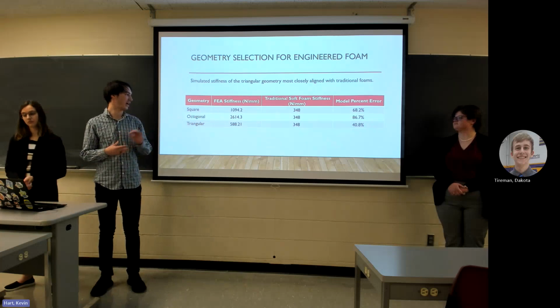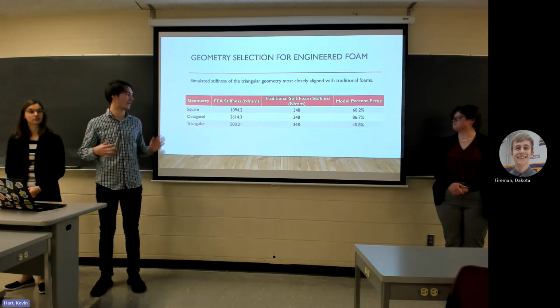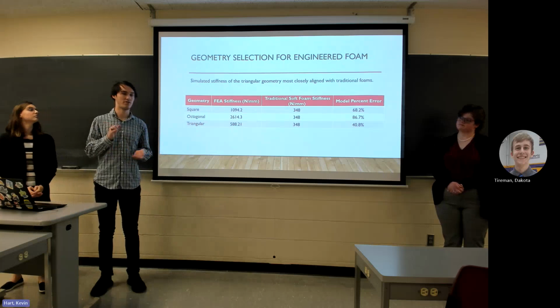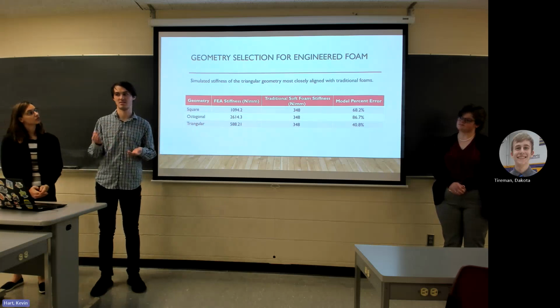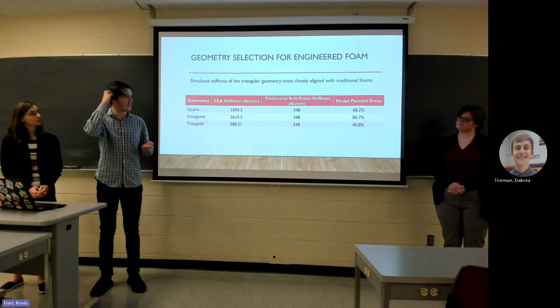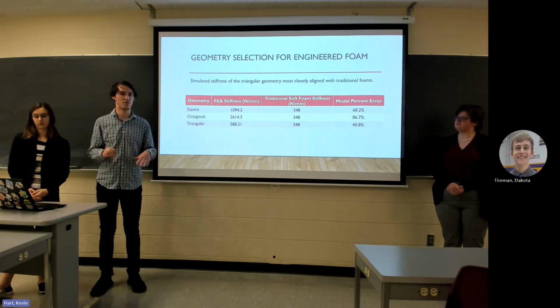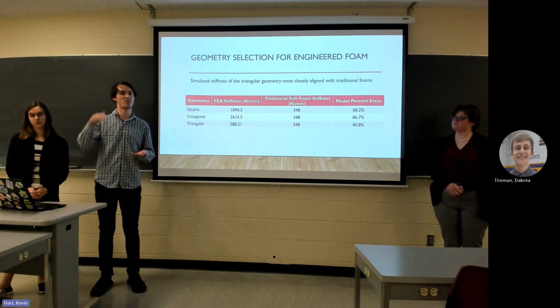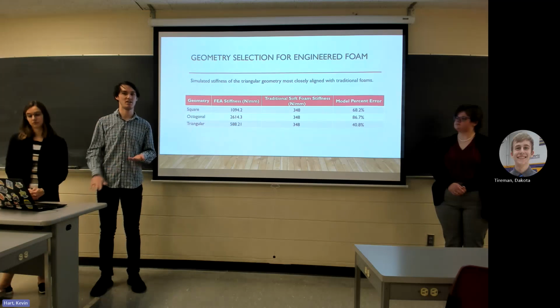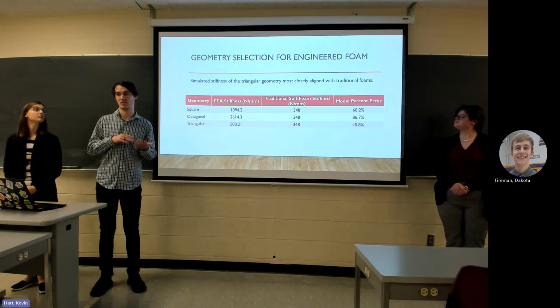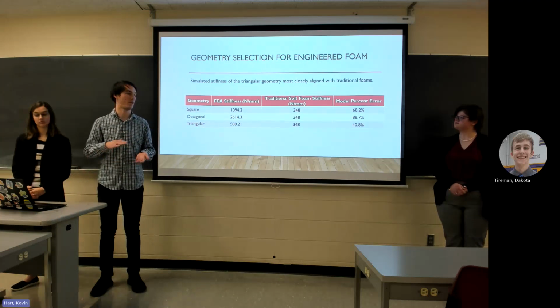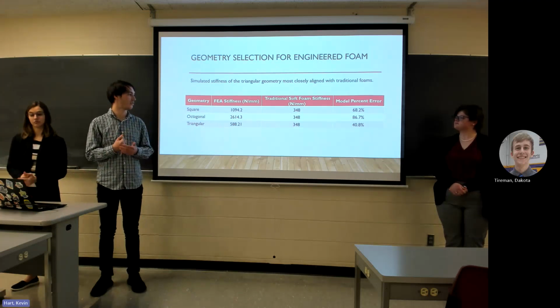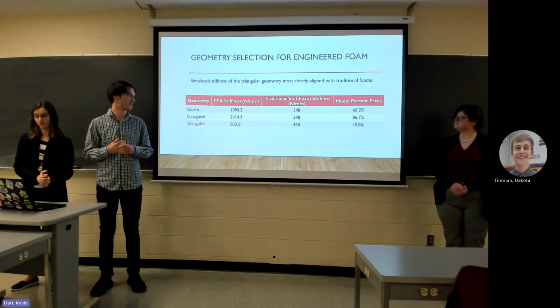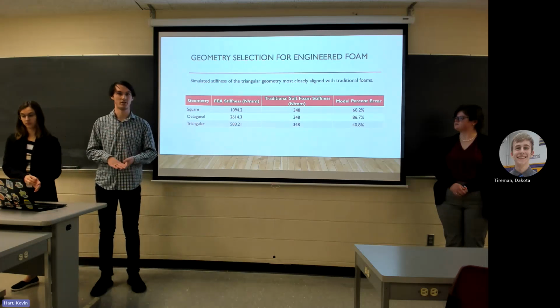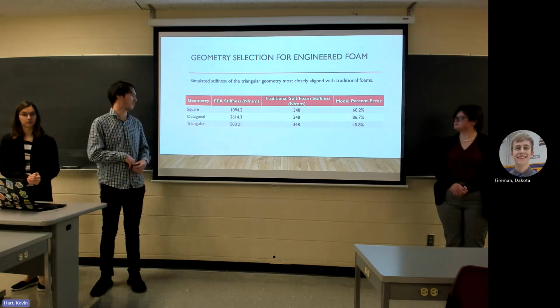And then we have promising results with the triangular geometry, since for all of the strut sizes for this foam FEA that we did, we had the strut size at 1.45 millimeters. So we still have the ability to decrease that and see if we can actually achieve the stiffness goal that we're looking for in the foam, since we'll still be above that 1 millimeter constraint in strut size.